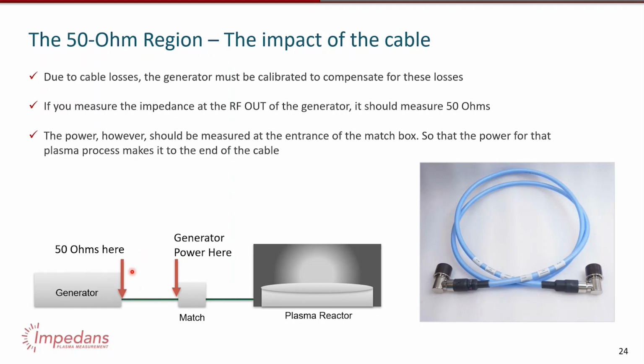Reality can be a bit more complicated than this because RF transmission lines are non-intuitive, but this is something you should consider. The other thing I want to mention is, people care that my generator needs to be 1% accurate or 0.5% accurate, but then they're not thinking about this cable, which would be draining 10% of the power, and they're not thinking about the matchbox, which has its own efficiency. Matchboxes have fans for a reason, they have water cooling for a reason. Power is lost in there, and the power is lost depending on the plasma and depending on the wafers. So your matchbox could be losing 5%, 10%, 15% or more power, depending on what process you're running at the time. So people fret a lot about this 1% at the generator, but there's actually a 10, 20% margin of error on this side in terms of power delivery.